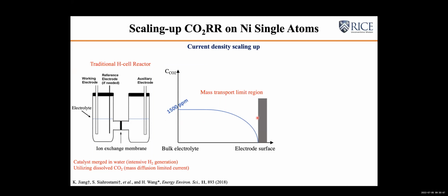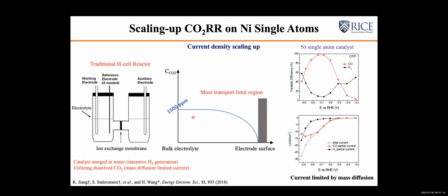So when you are reaching a significant amount of current density, to generate the CO product, let's say, you will deplete the surface CO2. And then eventually the limitation will not be the kinetic limiting step. It will eventually become the mass transport from the bulk CO2 towards the surface. That mass transport, how fast you can bring the CO2, becomes the limitation. So that's always the reason why we observed this phenomenon.